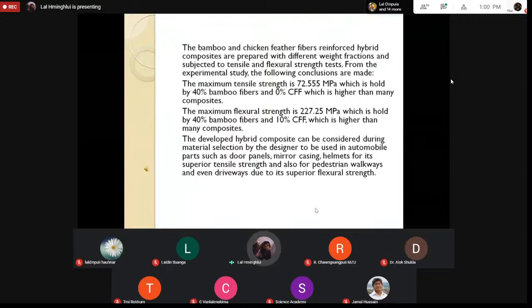So the bamboo and chicken feather composites are prepared with different weight fractions and subjected to tensile and flexural strength tests. From the experimental study, the following conclusions can be made. The maximum tensile strength is 72.555 megapascals, which is held by 40% bamboo fibers and 0% chicken feather fibers, higher than many composites. Also, we can see that 72.555 is the maximum tensile strength as compared to other concentrations. So at 40% bamboo fibers, we can come to the conclusion that the main contributor of the tensile strength in the composite for this particular experiment is the bamboo fibers. They are the main source of tensile strength.